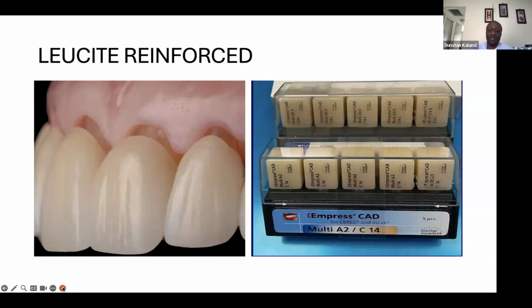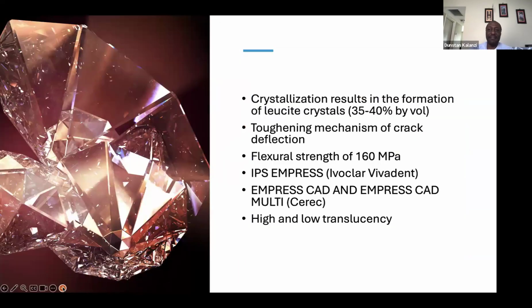And to just go into a bit of the physical properties, this particular material is crystallized, resulting in formation of leucite crystals. They make up 35 to 40% of the volume. And this results in a toughening or a crack deflection toughening mechanism. The flexure strength of the leucite reinforced comes to about 160 megapascals. They can have high or low translucency, but those who have used CEREC, the material would come as Empress CAD or Empress CAD multi.